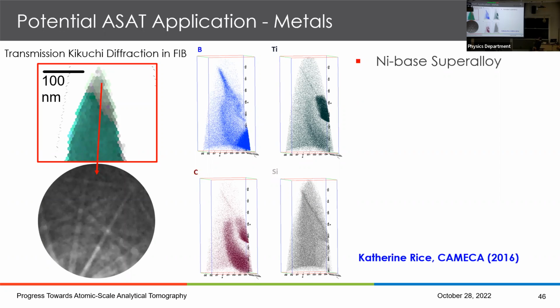All right, so it's a grain boundary. What do we know about it? Well, in nickel-based superalloys, 40 years ago, people figured out that if you put boron in these things, you can improve their creep resistance, but you create other problems. Boron is known to create, I think, some brittle behavior. So it's a blessing and a curse. And so the question is, how is it doing that? Basically people started finding, they think it was at the grain boundaries. Well, atom probe has been able to show that very nicely, that indeed in these nickel-based superalloys, the boron does tend to very strongly segregate to the grain boundaries. But it's not the only element. As you can see, titanium, silicon, and carbon also are segregating there.